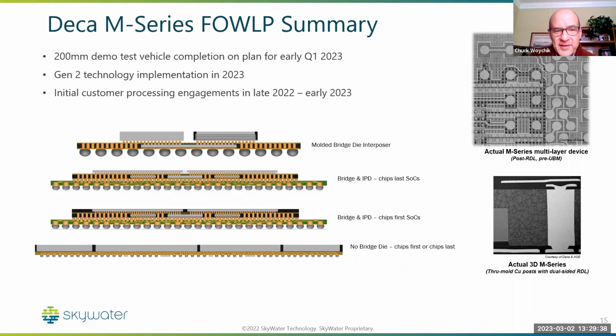So what's important here is you can see in these different configurations the different types of structures that one can build. The first one being a molded bridge die interposer. What's really important here, and part of SkyWater, we're involved with the ASIC consortium, is to show that with the finer lines and spaces of the DECA technology, many of these designs could be built without an embedded bridge interposer. We just can accommodate that with the finer lines and spaces in the build-up structure on the top surface.